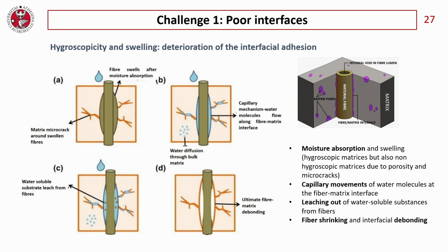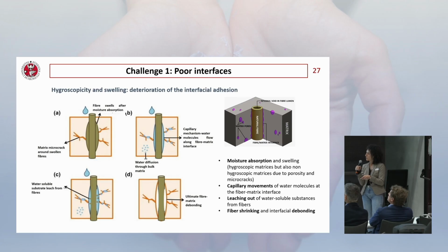Okay, starting back from the first challenge, the hygroscopicity of the fibers, the fact that they absorb a lot of water, causes a stress on the interface. In fact, you can see that if the fiber absorbs water, it can swell, and some water-soluble substrates can leach from the fibers, and therefore the fibers will shrink when the environment is dry again. And this, of course, decreases the interfacial strength with the polymer matrix.